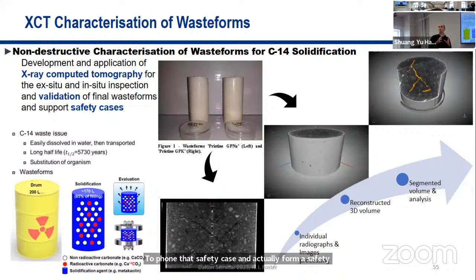One of the issues with the way that disposal is done in Korea is we have a set number of acceptance criteria, such as compression testing, leaching testing, which are all essentially a yes/no answer. For example, compression testing, you have to meet 3.44 megapascals. If you exceed that, then you can dispose. But the question is, what have you done to the waste during that procedure of compression? Likewise, leaching and things like that.